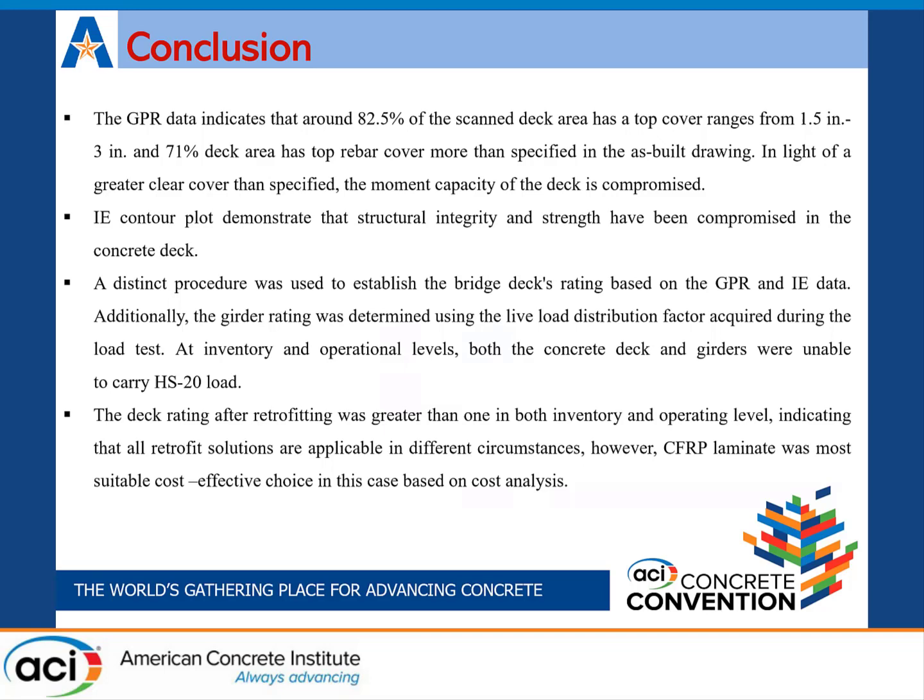As a conclusion, we can draw that 82% of the scanned deck area has top rebar cover between 1.5 and 3 inches. The IE contour plot demonstrates structural integrity and the strength of the deck has been compromised. A distinct load rating approach was established to load rate the deck.